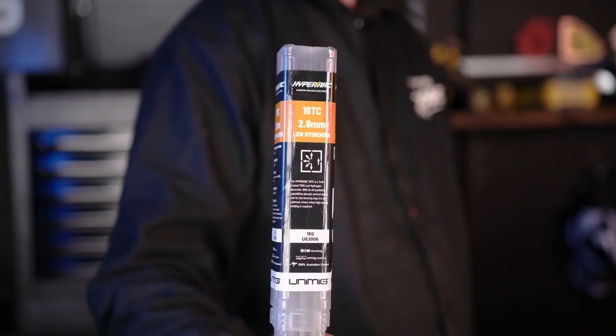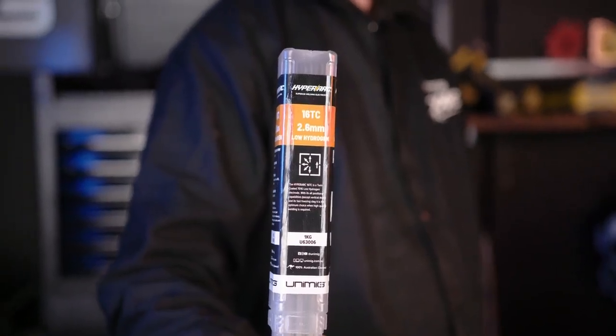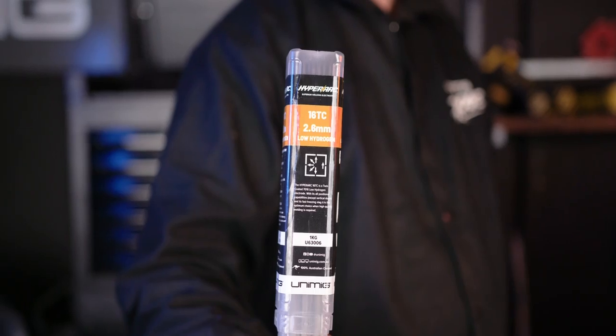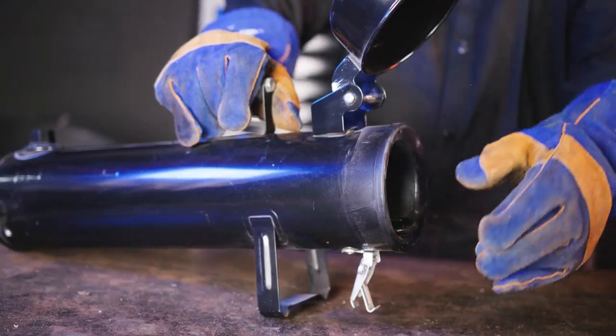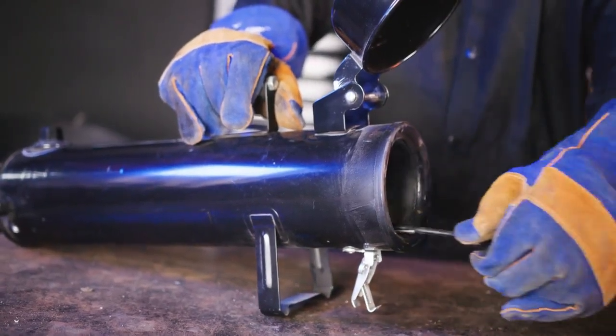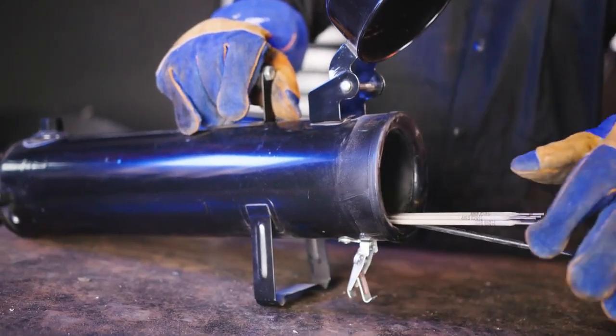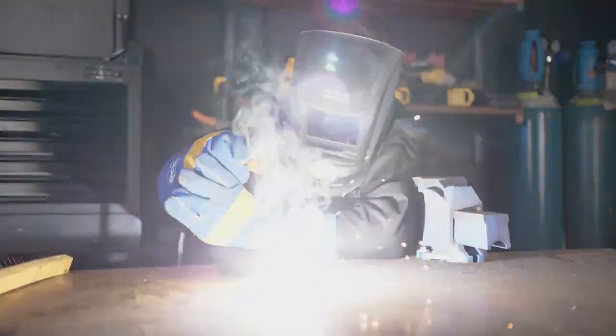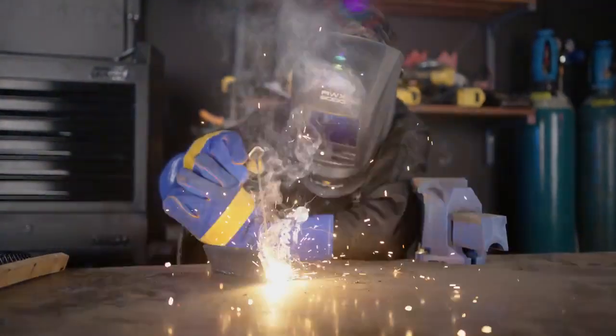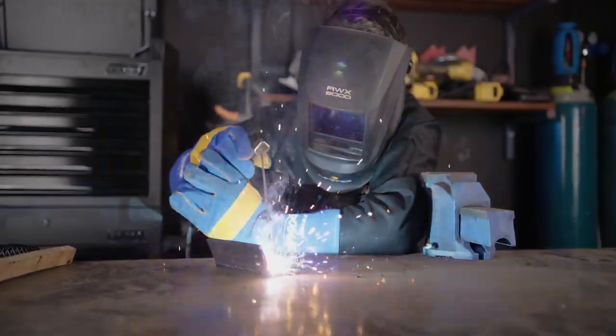Number 6, wet is bad. Generally, electrodes do contain some moisture in them. Excessive moisture, especially in low hydrogen electrodes, will cause problems such as wandering or erratic arcs while welding, but there is a solution if you come across this issue. Electrode ovens are designed to rebake your electrodes if they have been left out in an open packet for a while, but the best way to keep them in good condition is to store them in a dry place, preferably sealed, until you're ready to use them.